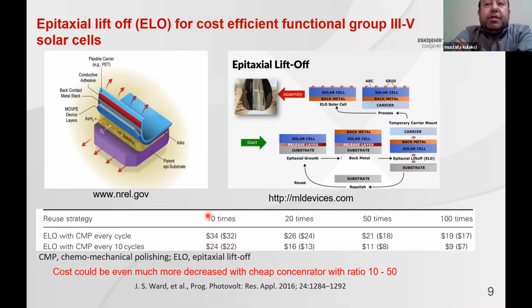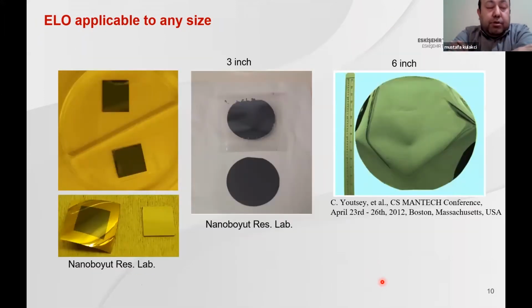Of course, by decreasing this device cost, you can also rebuild concentrated photovoltaic. Instead of high concentration ratio, you can build some low concentrators with a ratio between 10 and 50, and you can also decrease cost moreover, these guys 10 times maybe or more. Here you see the picture of liftoff of solar cell structures. Actually, you can apply an ELO structure from micrometer square up to full 6-inch. Actually, in 6-inch, maybe there can be problems in the industrial case, but up to 6-inch you can easily grow.